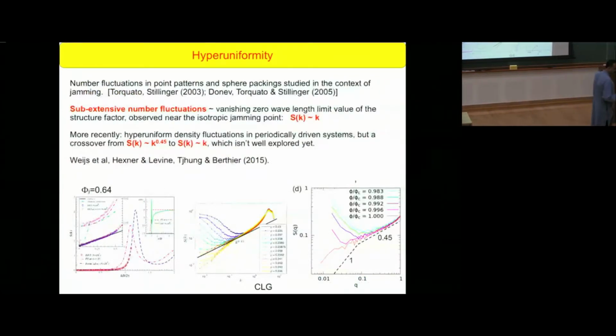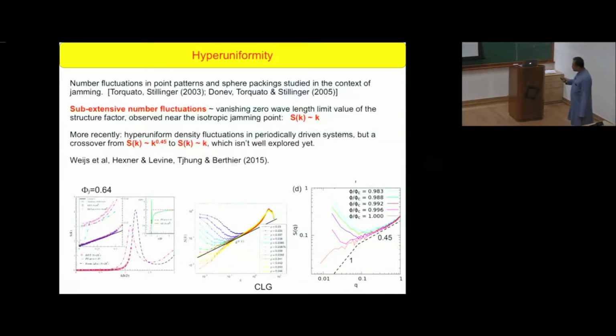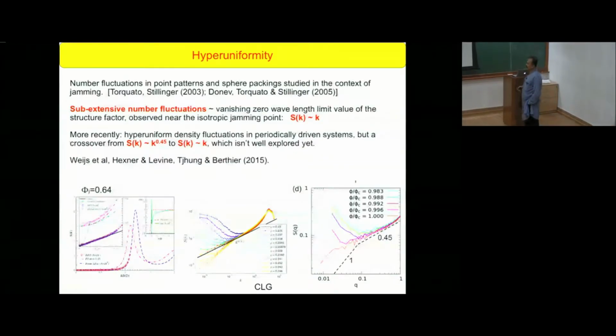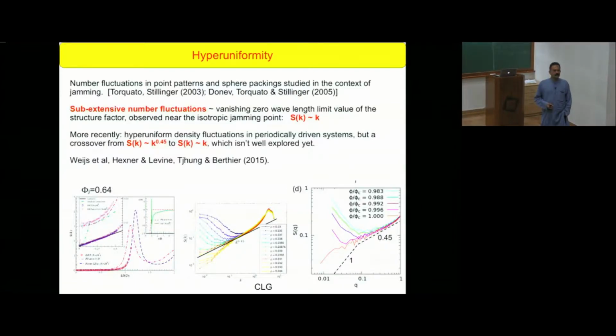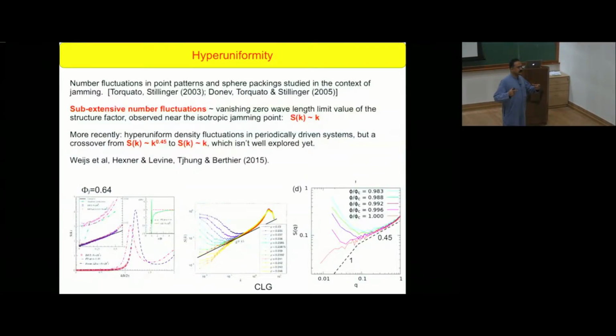So hyperuniformity is something that's been studied quite a bit for driven systems, among others. The basic idea is that if you look at number fluctuations in these structures, they are sub-extensive. If I look at the structure factor in the limit k going to 0, it vanishes, okay? And if I look at regions of different sizes, and I ask what is the variance in the number of particles, instead of going as the normal, proportional to n, the number fluctuation goes as proportional to n to some power which is less than 1, okay?